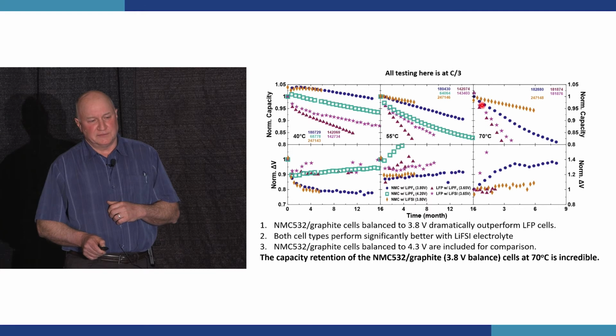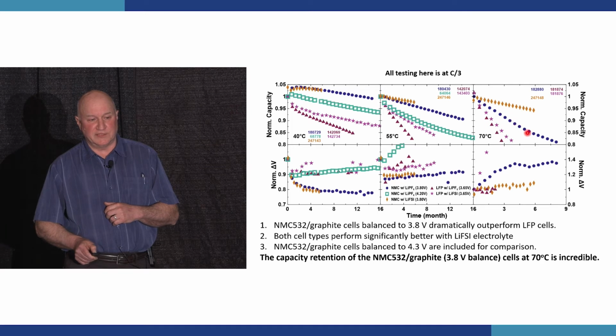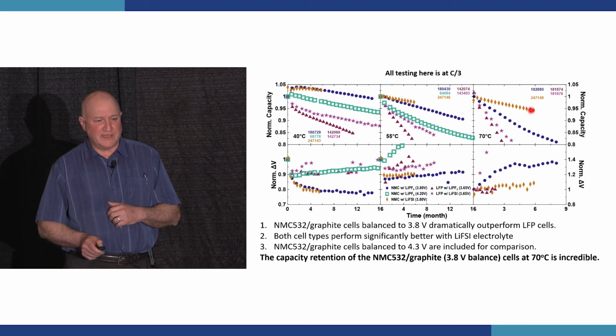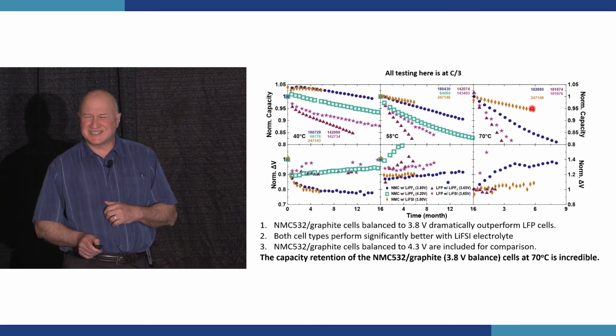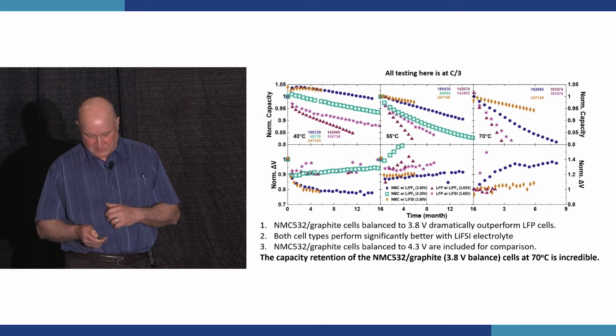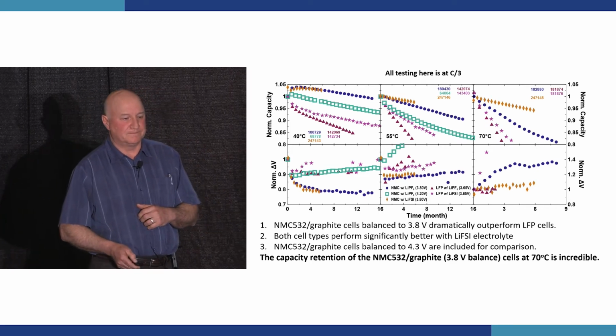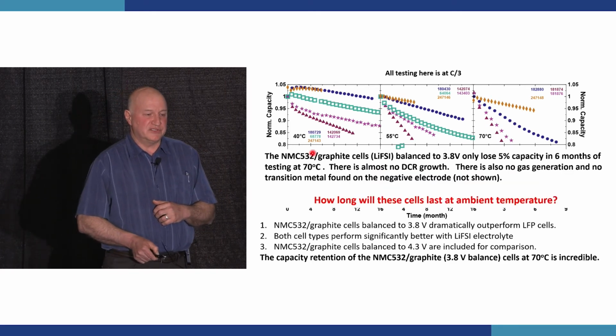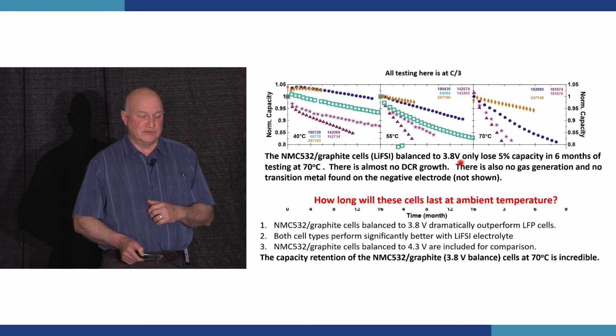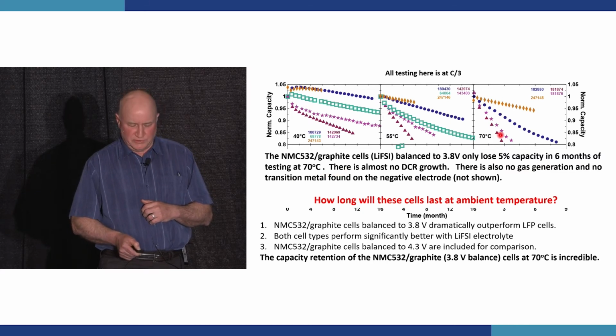And then the NMC 532 cells balanced for 3.8 volts with LiPF6 electrolyte salt are shown here in these purple circles. And then finally, these orange diamonds show you NMC 532 cells with LiFSI electrolyte salt. It's incredible. They've lost only 5% of capacity in half a year at 70 degrees C. It's crazy. So these NMC 532 cells balanced to 3.8 volts only lose 5% capacity in 6 months of testing at 70 degrees C.